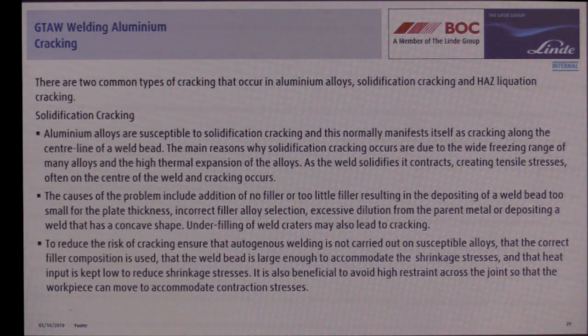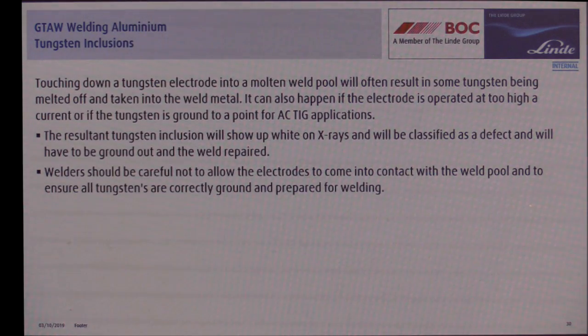Cracking: the same thing for TIG welding. Obviously, solidification cracking is an issue. Porosity is another issue, though not so much with TIG welding. And so we said about touching down a tungsten, that contamination will show up on an X-ray alongside any porosity that you have.